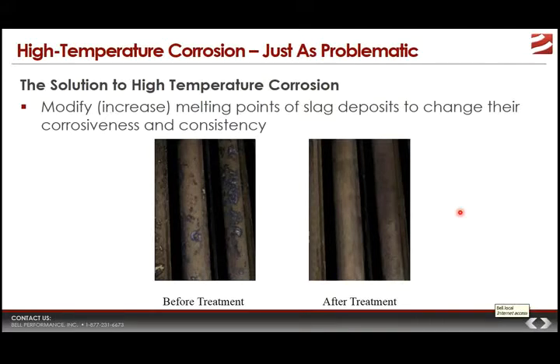Okay, as we said, hot corrosion is just as problematic, all things considered, as cold end corrosion is. What are the possible solutions to this? Well, first of all, you could try increasing their melting points. You can do something that will change their consistency and cause the melting points to go from, let's say, 600 degrees centigrade to 1200 degrees centigrade, and you would have a much greater chance of reducing these semi-liquid deposits that are corroding and damaging those tubes. And that's precisely what these folks did. They used a magnesium treatment to do precisely that.